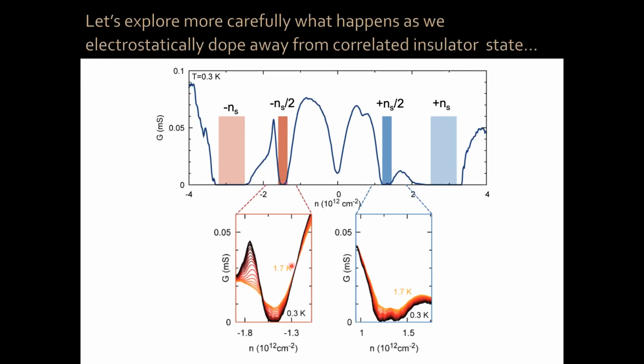So that's normal insulator behavior. When we look around the correlated insulator state for holes, for 2 holes per moiré unit cell, the insulator state itself also behaved like that. However, right next to it, we saw this conductance enhancement as we went down to lower and lower temperature. So we found that very, very curious. I remember when my students asked me, what should we do? Should we make more devices in a 4-terminal geometry to see how well this wants to conduct, okay?